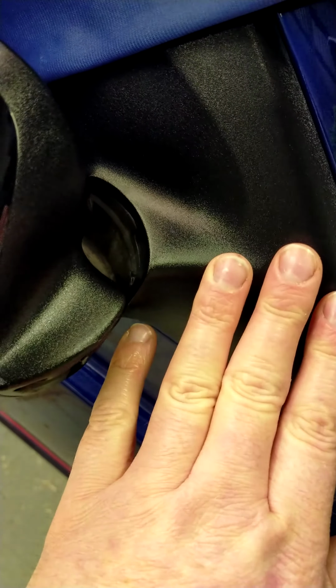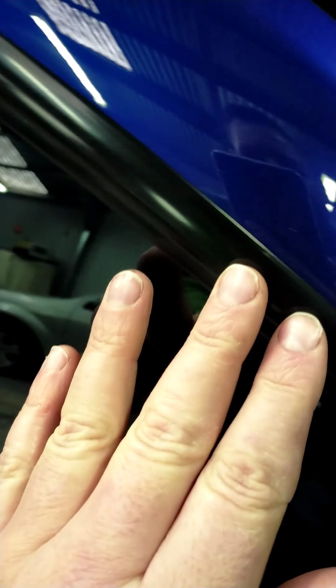Side mirror backings are the same as the Territory, but on this trim we have these vinyl-like materials that have a carbon black in them. This carbon black will eventually, with UV exposure over a long period of time, begin to leach out of the material, and it will become a very, very dull grey. Same with these as well. And with this car, no matter what I put on it, except for a true coating, these will dull off every single time I wash the car with water and soap.